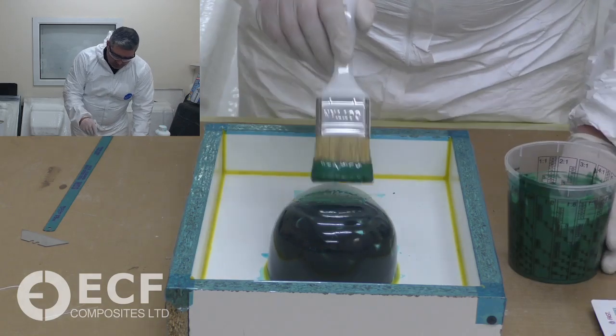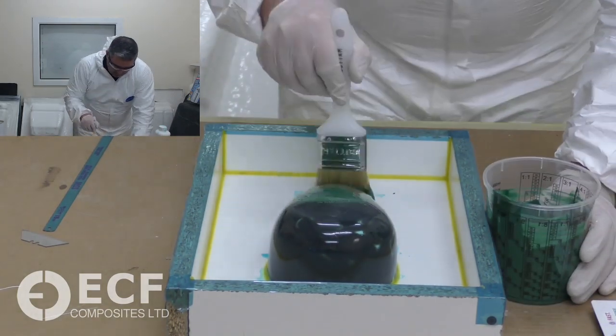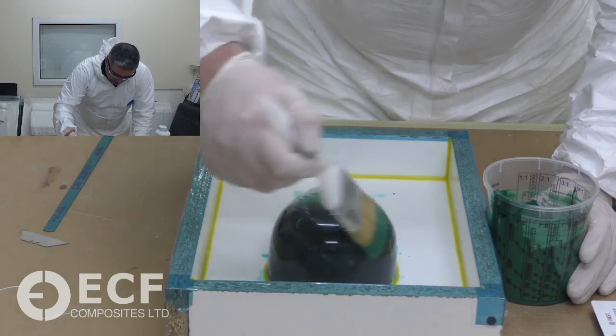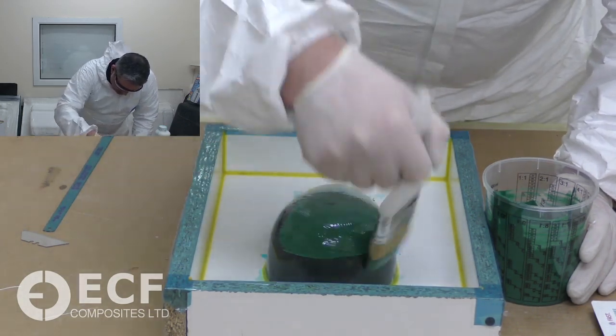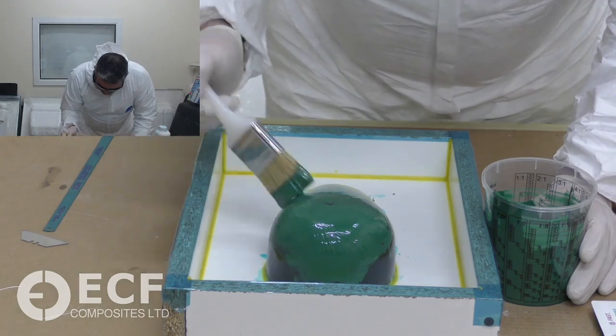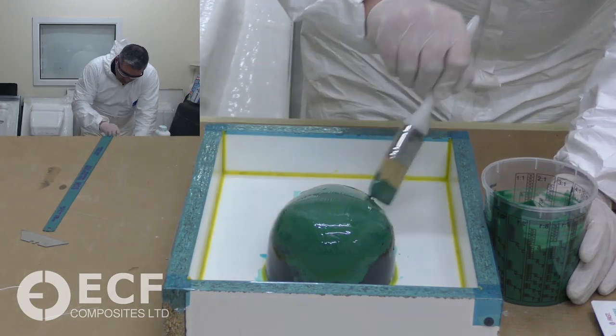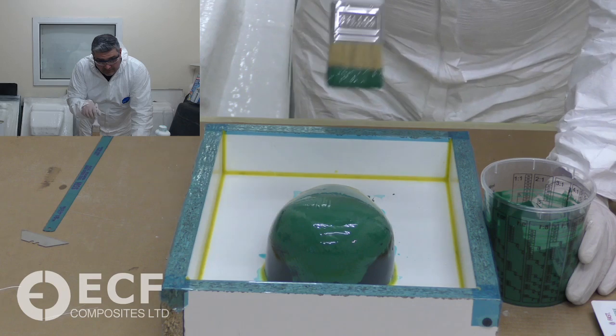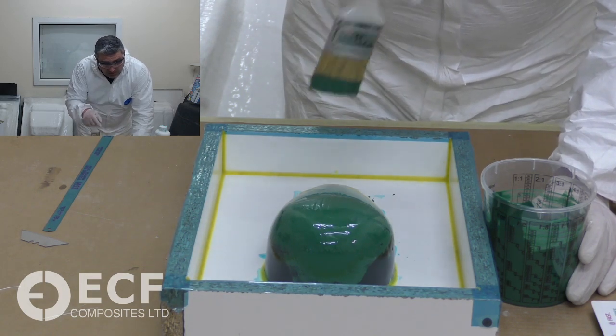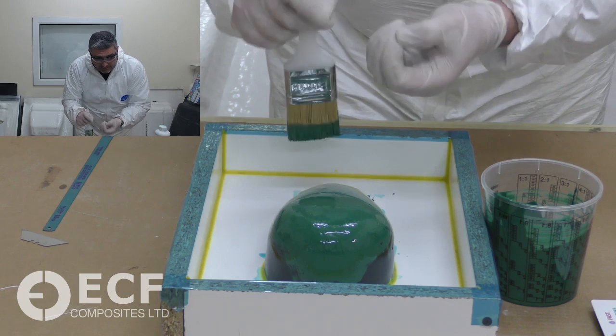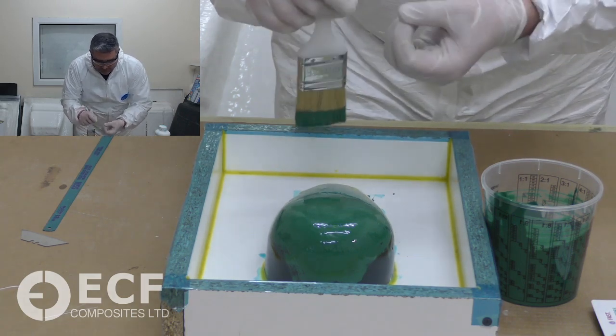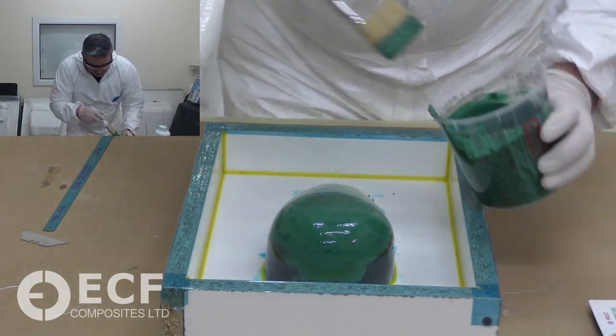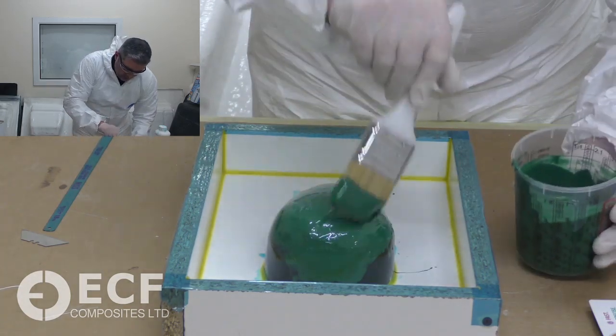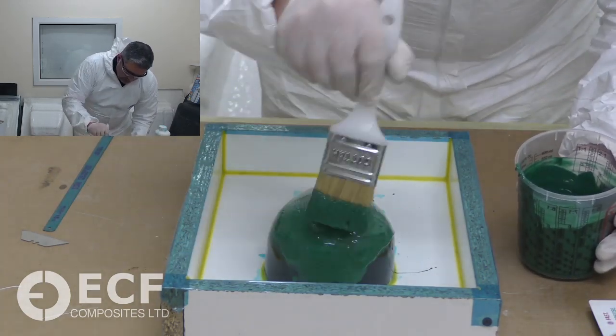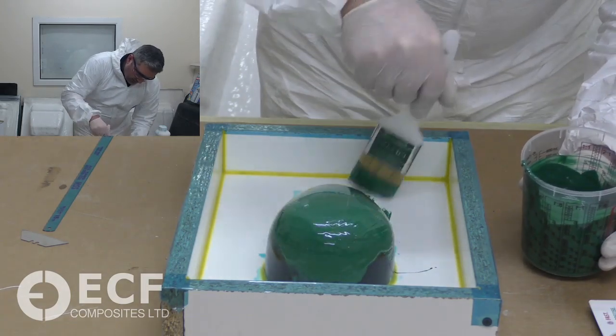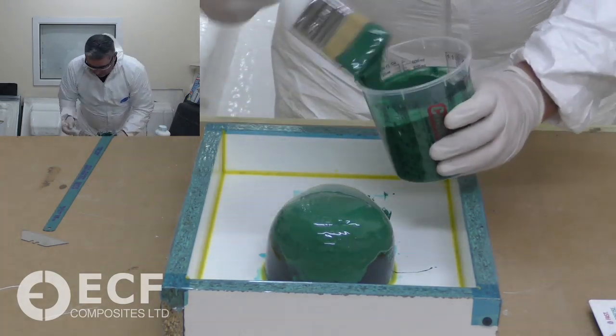Now what we don't want to be doing is treating this like a paint. We want to be layering it on. If you treat it like a paint and start doing this with it, you're going to end up with thin areas. And if your gel coat's too thin, it'll have that effect of pickling the gel as well, because it'll be too soft. It'll not have enough thickness to the layer to create its own exotherm, which it needs to cure properly. So we want to be applying it round about 0.6 of a mil thick, which you get just by spreading it on rather than painting it on.